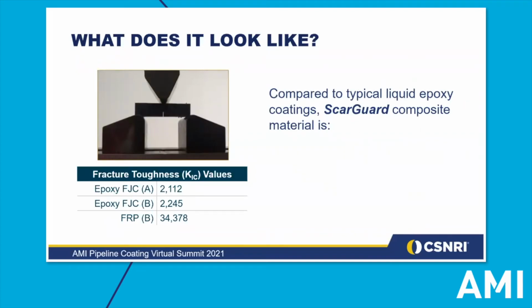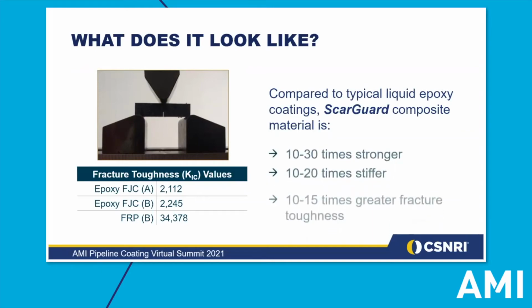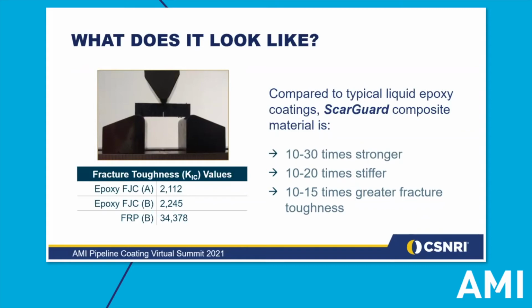We selected two commercially available liquid epoxy field joint coatings and several iterations of composites to perform these comparative tests. The test program showed that composites are 10 to 30 times stronger, 10 to 20 times stiffer, and overall composites possess 10 to 15 times greater fracture toughness than standalone epoxies. This was finally a lab report that validated what we have been witnessing in the field for so many years.